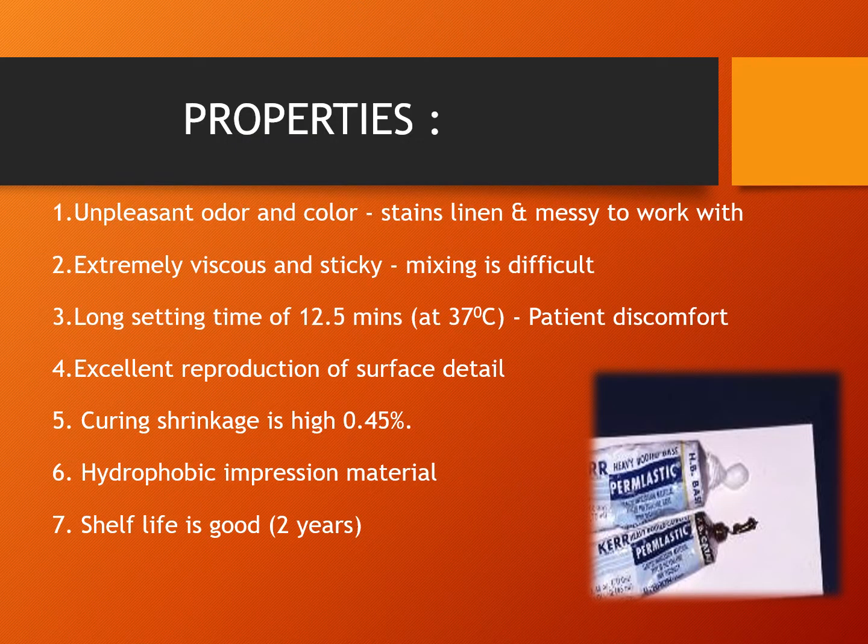Coming to the properties, it has unpleasant odor and color, it stains linen and it's messy to work with, it's extremely viscous and sticky while mixing, long setting time causes patient discomfort, excellent reproduction of surface detail, and curing shrinkage is high, that is 0.45%, and among the elastomers this has got the highest permanent deformation. It's a hydrophobic impression material, and so the mouth should be dried thoroughly before making an impression, and the shelf life is good, around 2 years.